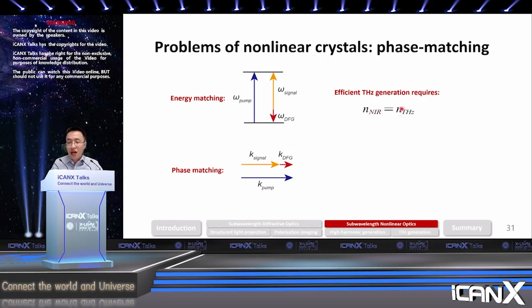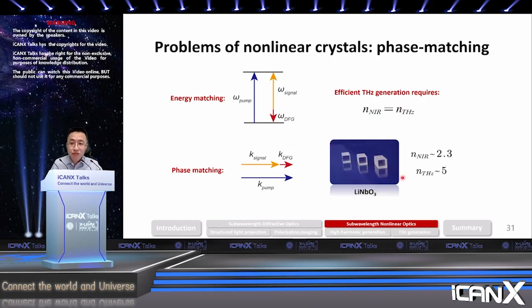As an example, take one of the most popular nonlinear crystals, lithium niobate. Because lithium niobate has an optical phonon resonance somewhere in the mid IR, its refractive index is drastically different in the near IR and in the terahertz. In the near IR it has a refractive index of 2.3, and in the terahertz its refractive index is 5. So many conventional methods for phase matching, such as quasi-phase matching or birefringent phase matching, probably don't work well for this purpose.